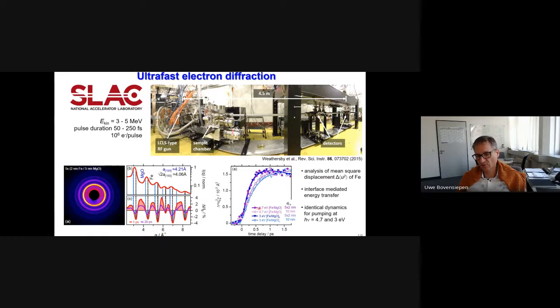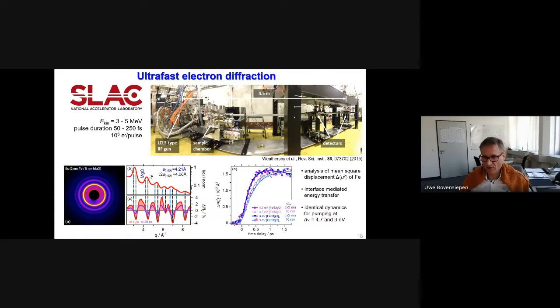What is the difference between the magenta and the blue data? This is the photon energy of the pump pulse. And we compare here the UV excitation of 4.7 eV, where we reach the conduction band of the MgO, and the second harmonic of the titanium sapphire laser, which does not reach the conduction band at 3 eV. And basically the response is identical.